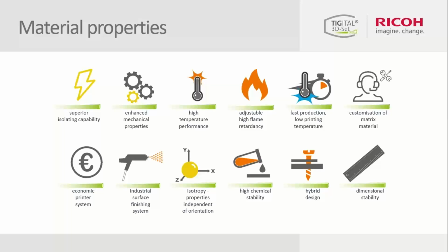And one of our key and also unique selling points for our material is the adjustable flame retardancy. The materials are not dripping during the burning step, and we can adjust it up to UL94 V0. One point which we would like to highlight is also the fast production and low printing temperatures. What does low printing temperature mean? We are printing below 70 degrees. Our printing window is between 64 and 68 degrees, and we can print our materials in that range. And we are using the same SLS printer with an open platform. So our materials can be used in any 3D printer with an open platform.